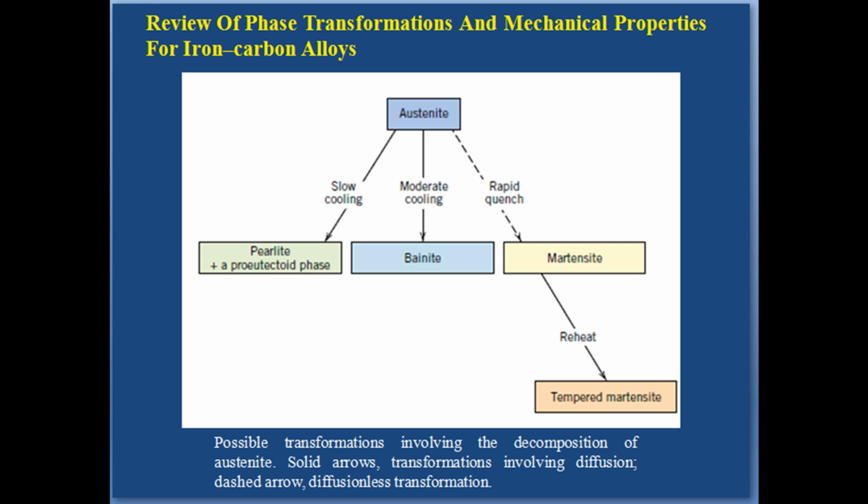The reason for this behavior relates to phenomena that occur at the alpha-ferrite/Fe3C phase boundaries. First, there is a large degree of adherence between the two phases across a boundary. Therefore, the strong and rigid cementite phase severely restricts deformation of the softer ferrite phase in the regions adjacent to the boundary. Thus, the cementite may be said to reinforce the ferrite. The degree of this reinforcement is substantially higher in fine pearlite because of the greater phase boundary area per unit volume of material.